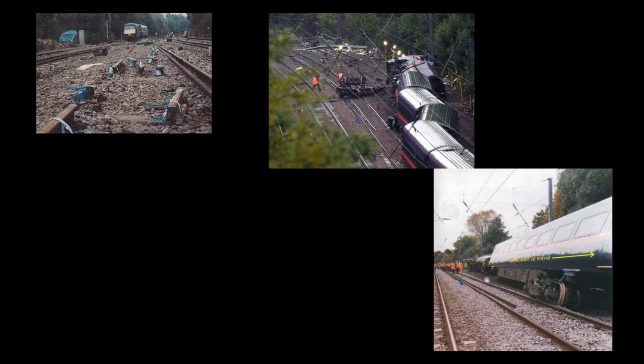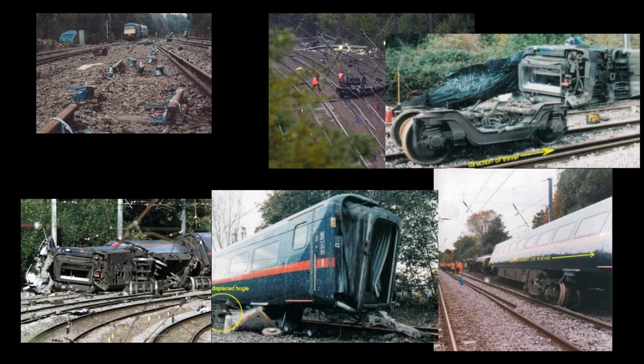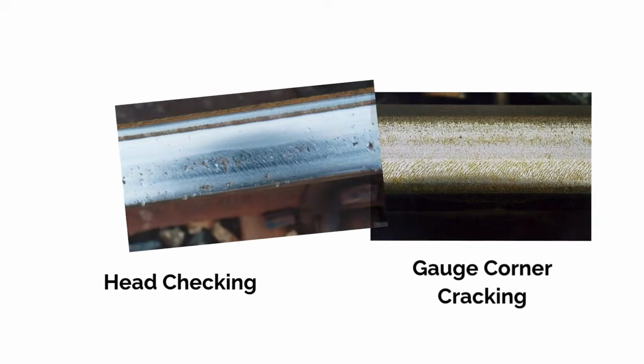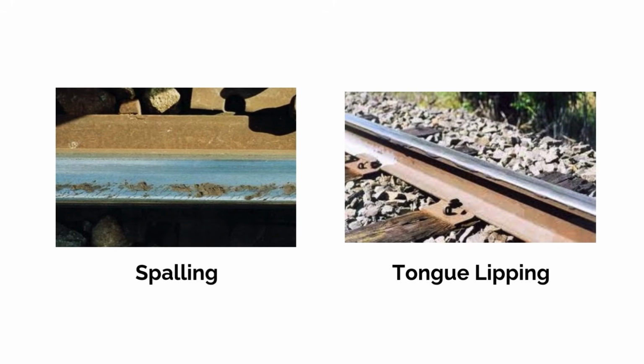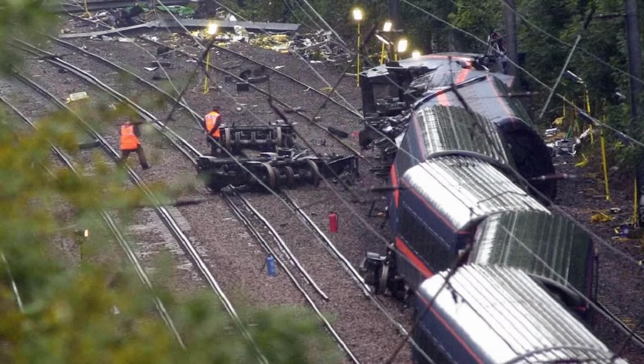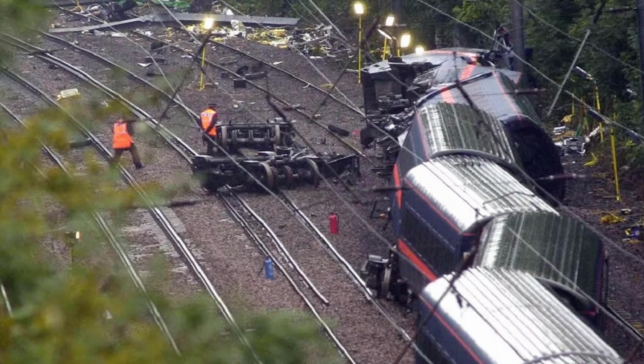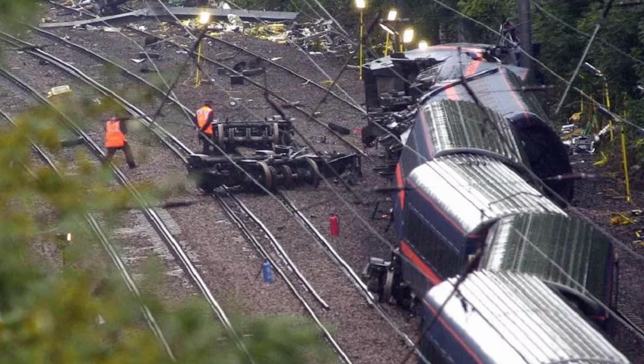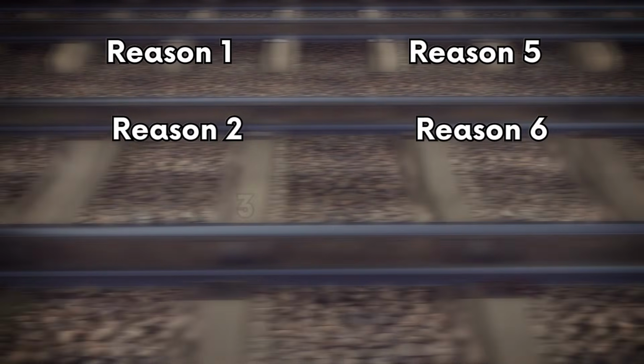The most well-known surface defect is rolling contact fatigue, the defect that led to the deadly train crash at Hatfield in 2000. RCF, as it's commonly known, can appear in a number of forms, from head checking and gauge corner cracking to spalling and tongue lipping. The danger from RCF and other surface defects is not primarily the damage to the rail surface itself, it's the propagation or growing of the cracks. As they grow, cracks can join up, leading to parts of the rail breaking away.